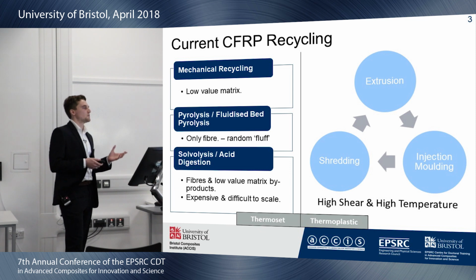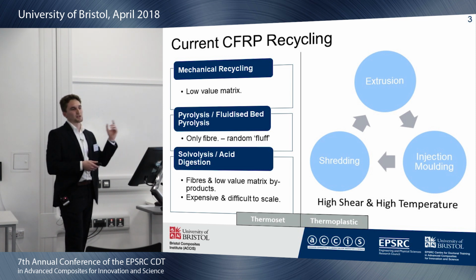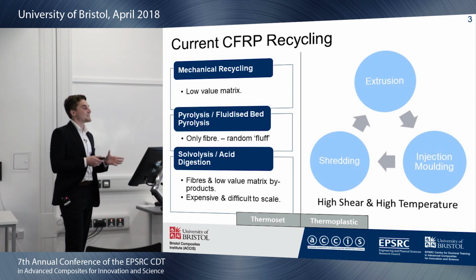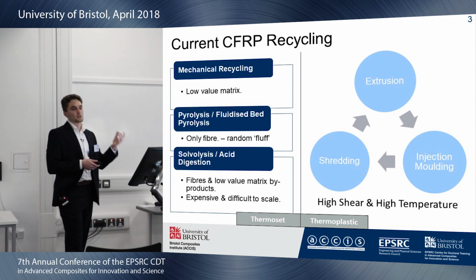But with those fibres, unless you have a remanufacturing process that's of the correct scale and the right process, you won't be able to get the randomly oriented fluffy fibres into enough of an orientation so that you can get a high volume fraction, which is what you need to get high performance and high value recycled components. So for thermoplastics, you normally extrude, injection mold and shred, and you can do that over and over again. The problem with that is that you degrade your polymer structure and your fibres so much that the recyclate is of a low value after every iteration.